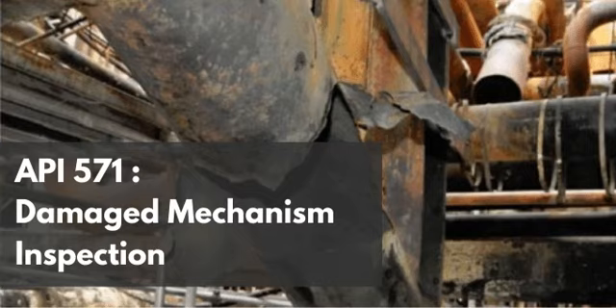Extruding fins is a severe cold working process. Right, because you're not melting it. No, you are physically forcing the metal through a die at room temperature, radically deforming its crystalline structure just to pull those fins up from the base material. Yeah, this process fundamentally destroys the relaxed grain structure of the brass and locks an immense amount of permanent residual stress into the tube wall.